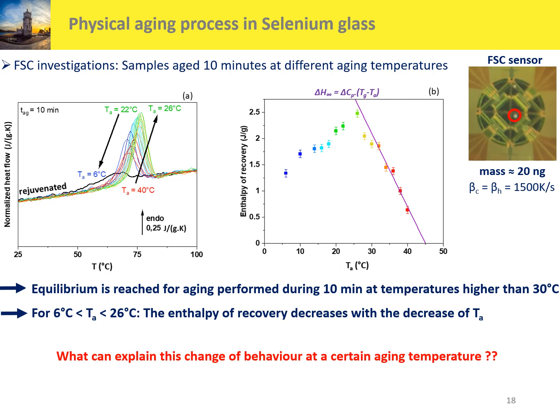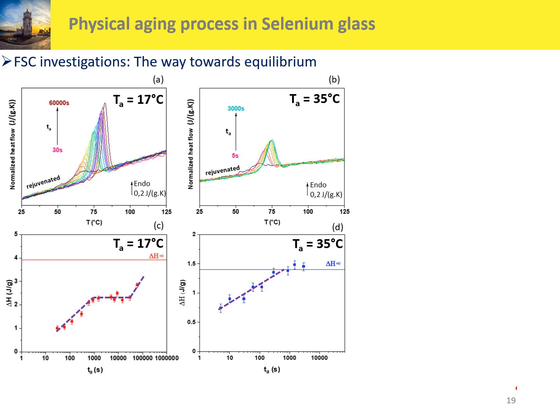So, what can explain this change of behavior at a certain aging temperature? To try to find an answer, we perform aging far from Tg. Tg is equal to 40 degrees C for selenium glass. And we perform also aging close to Tg. Here we have the experimental curves obtained for Ta equal to 17 degrees C, and for Ta equal to 35 degrees C. So here, far from Tg, and here, close to Tg.